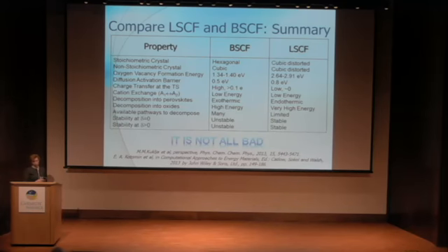in LSCF. Oxygen vacancy formation energy is lower in BSCF. It's almost twice higher in LSCF, but it's not too bad. So 2.6, anything close to 2.9 is actually still suitable for these applications. It's the same as diffusion activation barrier. It's very low in BSCF, it's 0.5, and it's 0.8 to 1 eV in LSCF, and so forth. So there are a whole bunch of different properties which can be compared.